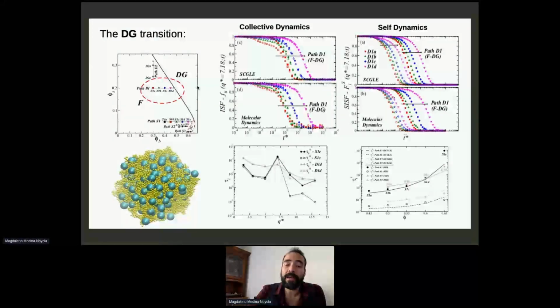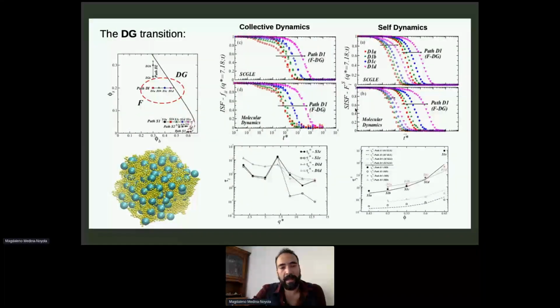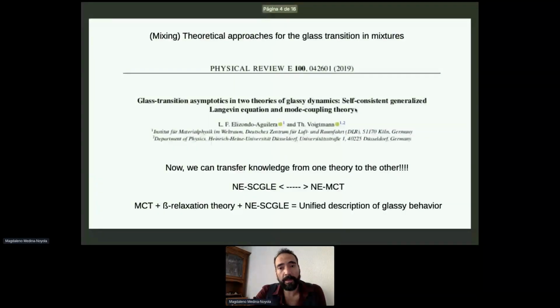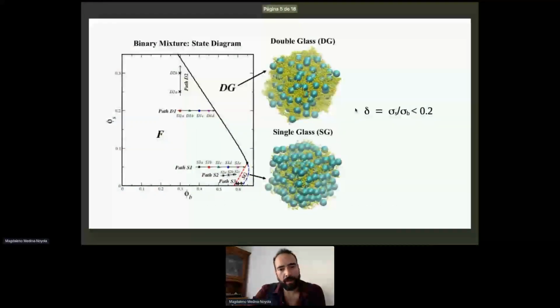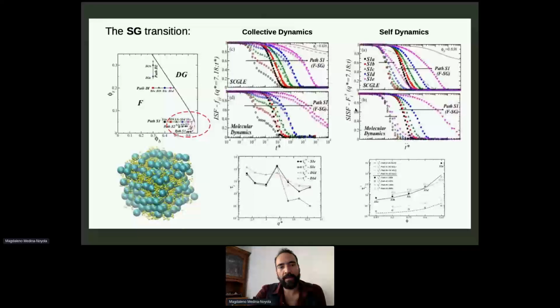And one immediately recognizes different patterns for the relaxation of both the collective relaxation times, but also the self-correlation times, which become correlated and both increase simultaneously, describing this physical scenario in which the small particles slave the big particles. So once we have characterized this system, I want to emphasize that we use these two theories that I was referring to, the mode coupling theory and the Langevin approach, through many years to characterize these features of a glassy system.